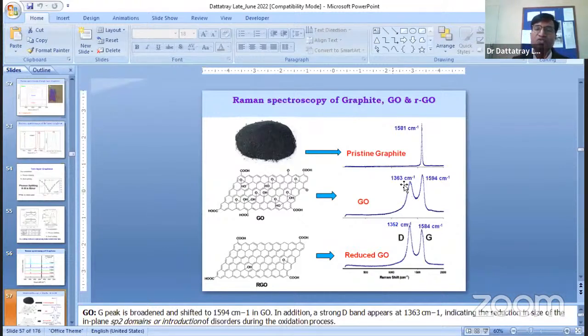So in addition to the G band, we also have this D band, that is the defect band. That will be around 1363, and you can see this G band, the peak position around 1581, shifted towards 1594. This becomes slightly wider, and this really tells some physics behind it.